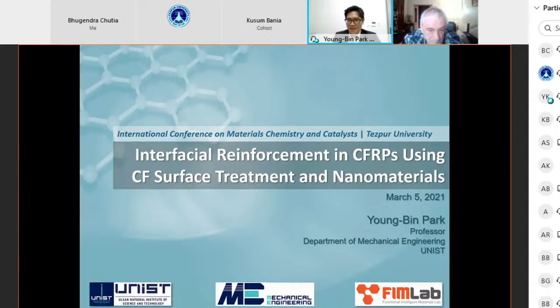And finally, this is polydopamine functionalized graphene oxide composites. In this case, I worked with a chemist at our university. He functionalized graphene oxide with polydopamine, which is a naturally occurring, in this case, synthesized bonding agent, which can help enhance the interfacial bonding between graphene oxide and PVA, which served as the matrix material in this case. So not only polydopamine functionalization promoted interfacial strengthening, but also we were able to use this as a sensor for moisture detection.